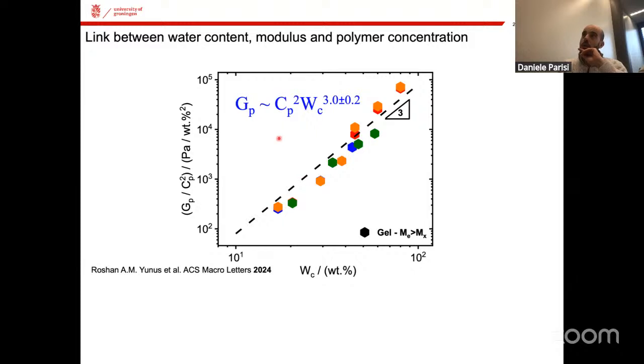So we were able to determine a scaling law that is very powerful in terms of materials design, because you can choose the modulus that you want the gel to have, and then select the polymer concentration and the water content that you need. If you know 2 of them, you automatically get the third one from this equation. Or if you start from a polymer concentration and you start adding a certain amount of water, you can already predict what the modulus could be. And usually modulus means elasticity, and elasticity means processing.